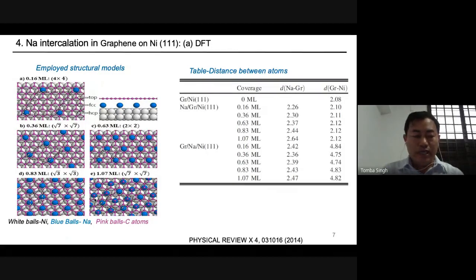To better understand the experimental results and our experiment, let's first present the DFT results, density functional theory results. This is the simplified structural model. In this model, the white balls are the nickel surface atoms, and the pink balls represent the graphene. In this top view, we see the graphene hexagons above the white balls of the nickel substrate.